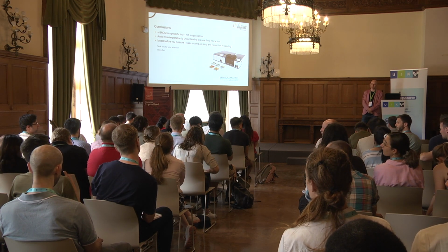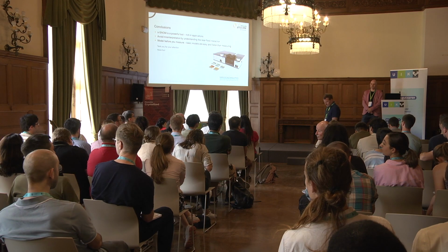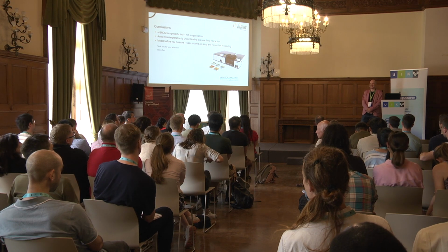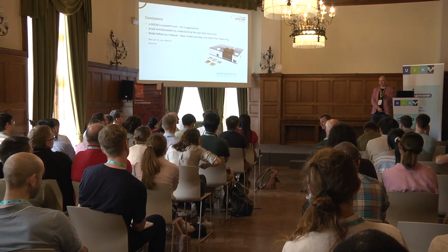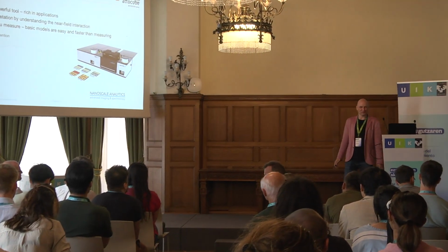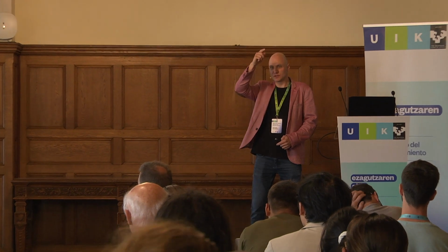Okay, and another question: you rely on this approach or retraction curve and compare it to experiment. But in fact, in experiment, you don't measure the pure near field. You measure high harmonics. What should you do? You can still measure the approach curve demodulated. Yeah, that's true. I kind of mixed two things together just for the sake of simplicity, and I really like that you picked it up. I was expecting somebody to do this. Let's put it this way: in order to mimic the experimental approach curve, you still need to calculate the full approach curve without demodulation, and then assume that you demodulate, right? And if the model captures one right, it will capture the other right. But they're not the same, that's true. There's a distinction.